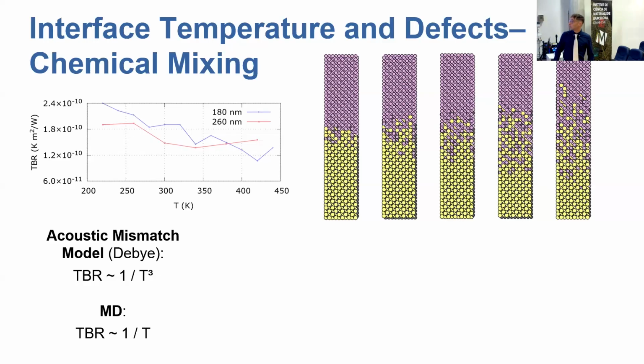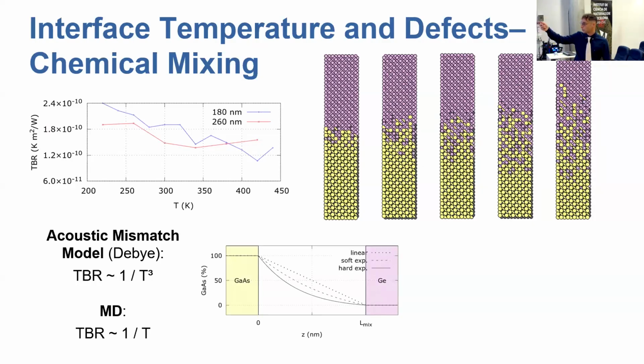Here you can see a snippet of the chemically mixed junction for different mixing length. With mixing length, I refer to the length of the region where chemical mixing takes place. In order to do this, we performed the random substitution of gallium arsenide atoms with germanium atoms, and we also did this with 3 different concentration decay kinds.